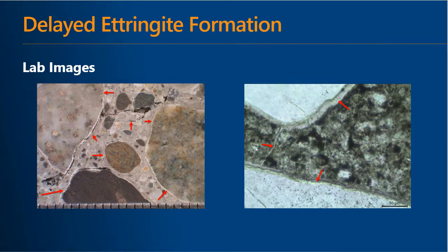So it's causing a bulk paste expansion, and the paste is pulling away from the aggregate particles. That results in these separation fractures around aggregate particles. We call them racetracks around aggregates that then fill with deposits of ettringite. But I do want to point out that these deposits of ettringite, typically in these types of cracks, are not